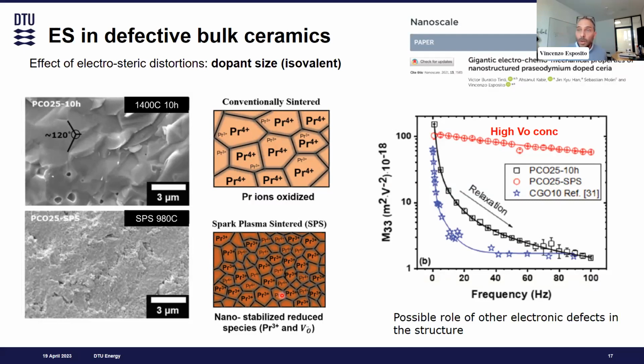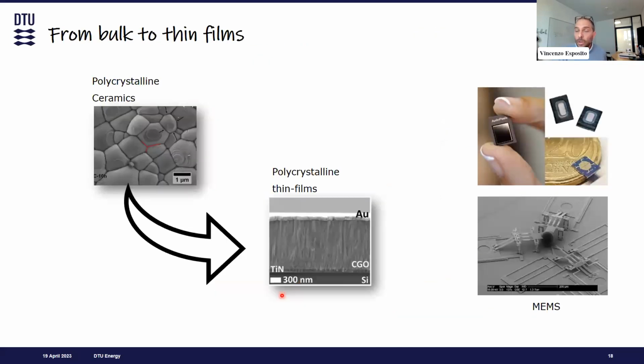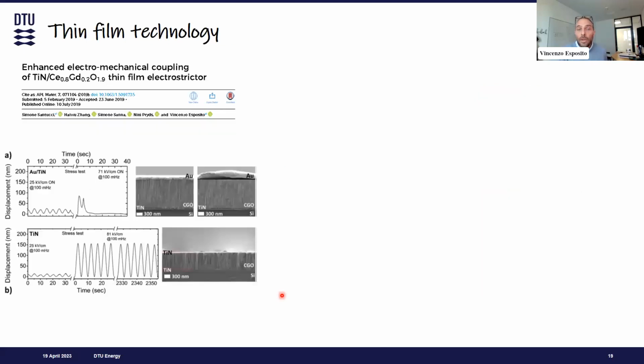So far, I've been discussing just experimental results. It's a phenomenological approach. I can also extend this to the thin film part, because thin films are extremely important, especially when we go to miniaturization and especially the deposition on silicon and other substrates for microelectronics. Because the current state of the art is based on piezoelectric and ferroelectric materials that sometimes are very difficult to process, while our cerium oxide, our oxygen-defective oxide, is straightforward. I have an example here where, using some ceramic electrodes, for example titanium nitride, we can have a direct deposition of a material that gets very stable.